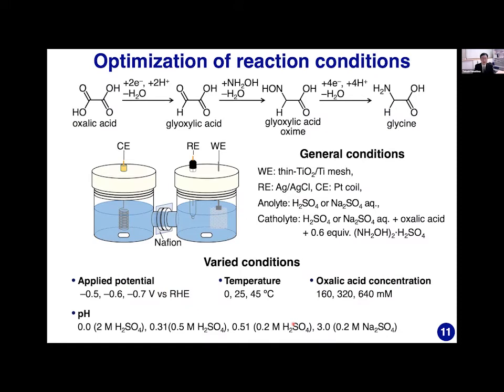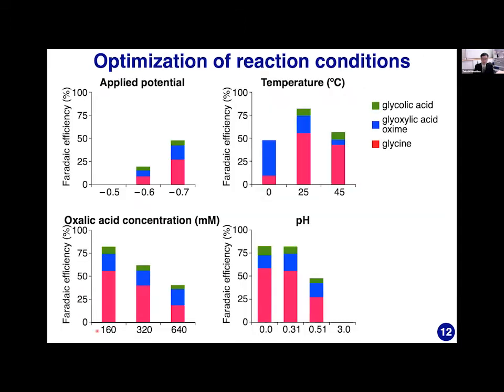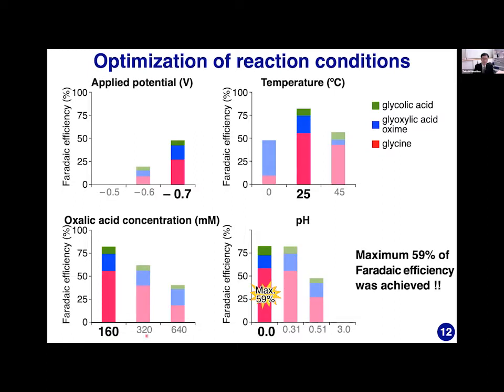Then we optimized the reaction conditions for glycine electrosynthesis to maximize the product selectivity. We optimized the applied potential, temperature, oxalic acid concentration, and pH. This slide shows the results. Finally, 59% Faraday efficiency for glycine production was achieved.